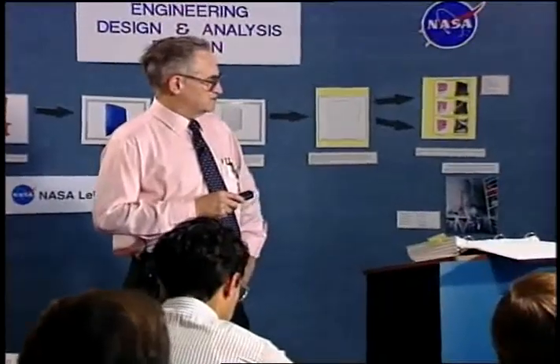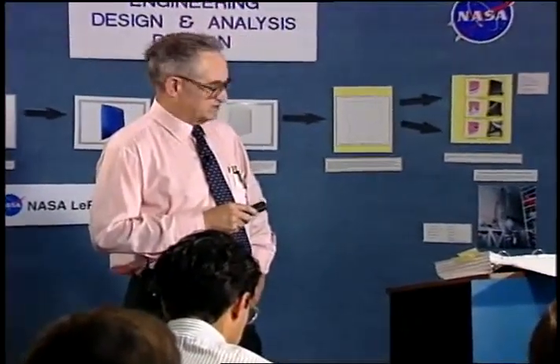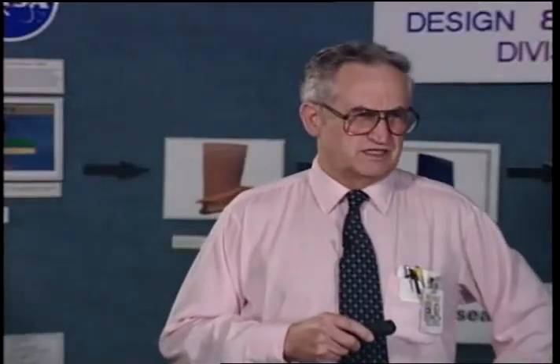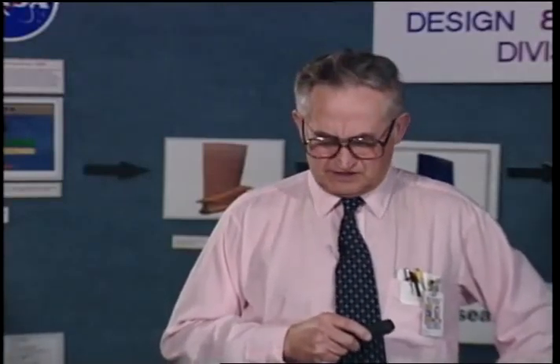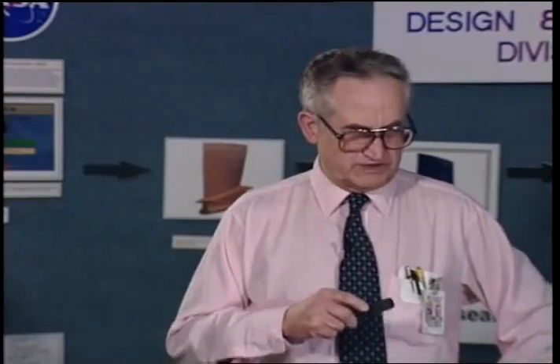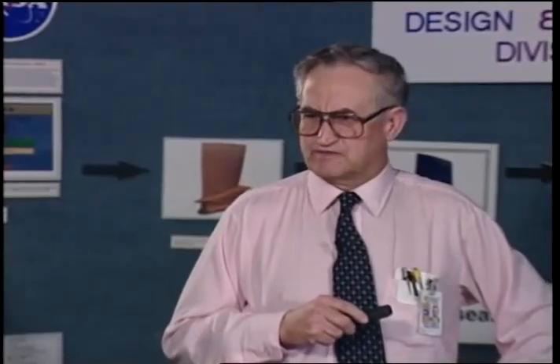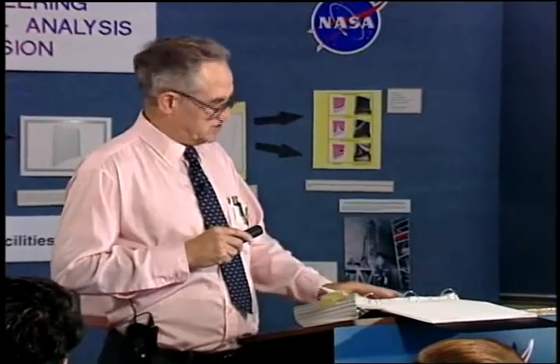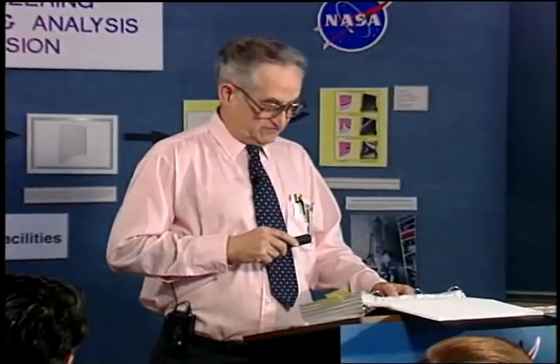So the only thing that you can do is test for it. And the way they test fasteners for hydrogen embrittlement, they put them on a fixture. There's an ASTM spec, which I don't remember the number of. You actually put them on with a wedge type washer and tighten them down and leave them for, I think it's 48 hours or something like that. If the head didn't pop off, it passed the test. And so what they do on testing for hydrogen embrittlement is just take a bunch of samples and test them that way to see if they can find where any of them have embrittlement.